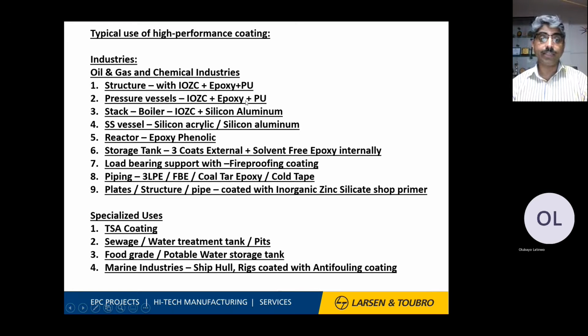Pressure vessels, again the same stack, again because boilers operate at high temperature. So zinc with silicon aluminum. Now we can say zinc melting point is 420 degrees C. So if you put this with silicon aluminum, it enhances the coating life to 650 degrees centigrade temperature.